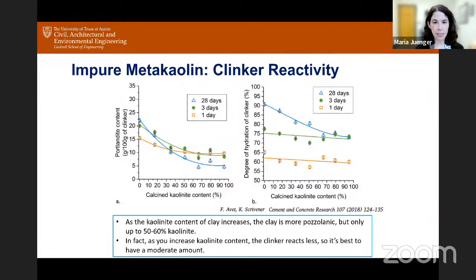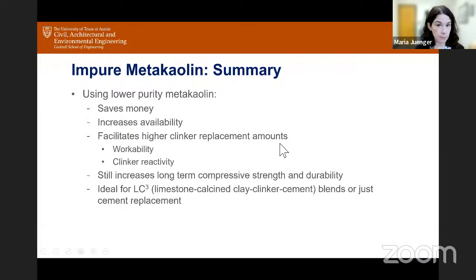effectiveness of the cement to hydrate by adding more lower purity kaolinite. So having a lower purity kaolinite allows your cement to hydrate fully. So again, pushing for this concept of lower purity is better. It helps workability, it helps you get adequate strength, but it helps optimize the efficiency of your system as well. It also saves money. If you use less pure material, no one else wants it. In the other cosmetic industries and other higher dollar industries, we save money. We increase availability because we can explore a wider variety of sources that other industries aren't using. And we can still get the benefits that we have from those systems.